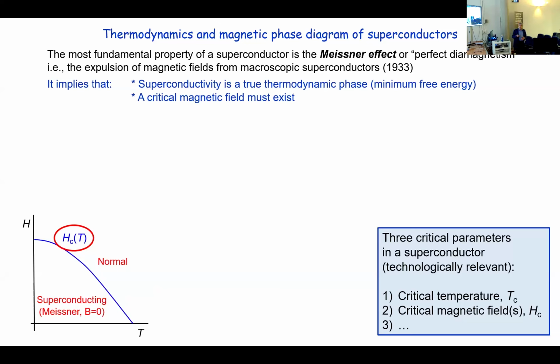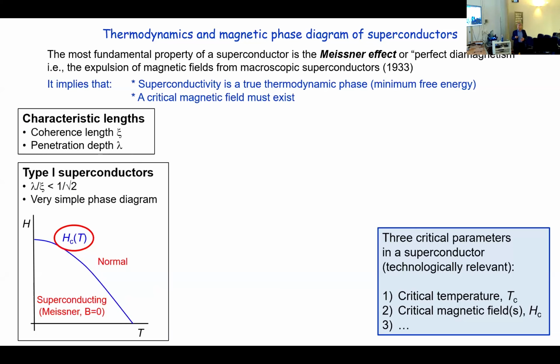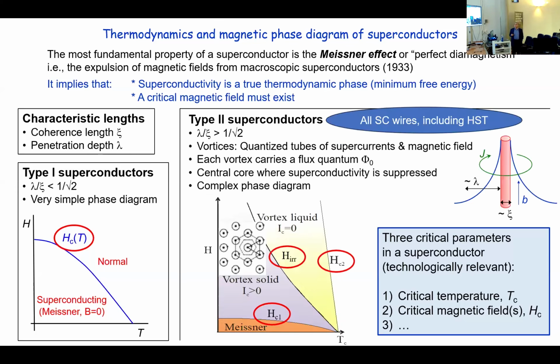So this is the second property, the critical magnetic field. In reality, there are several critical magnetic fields. Without entering into many details, there are two types of superconductors, depending on two characteristic lengths that are the coherence length and the penetration depth. I don't have time to go into detail on that, but type 1 superconductors have this very simple phase diagram, and they are not particularly useful except for superconducting cavities, but not to make wires. And then you have type 2 superconductors. All superconducting wires are type 2, including the HTS.